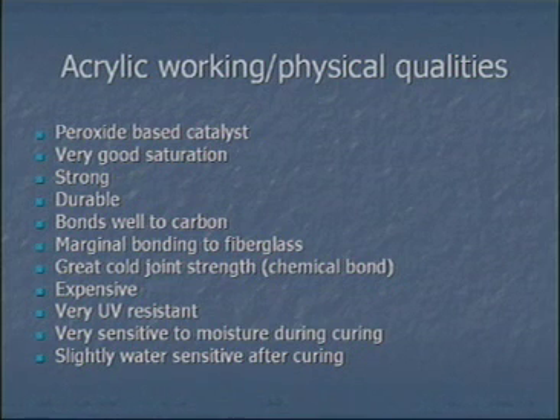They have really good cold joint strength, and this is how they're somewhat different than all the rest of the resins. These resins actually have a chemical bond that happens, so when the new resin is placed over the top of the old resin, it actually melts into the old resin and makes a chemical bond that's very strong. So that's a good thing. They tend to be very expensive, and they are very UV resistant, so they're not going to yellow. You could put these outside and they're going to stay clear and not yellow.